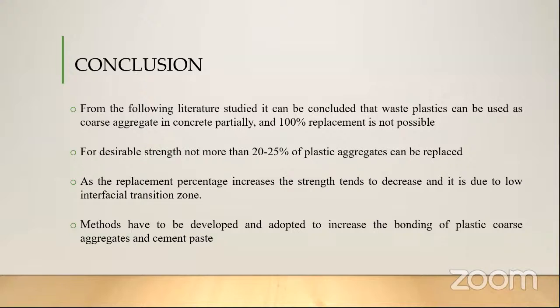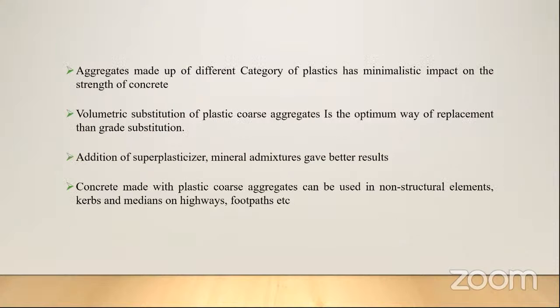So the conclusion derived from the literature is that waste plastics can be used as a coarse aggregate in concrete partially, because 100% is not possible. One of the major reasons is the low bonding between the plastic coarse aggregates and the cement paste, which leads to a weak interfacial transition zone. It was more of a unanimous finding among all the researchers that not more than 20 to 25% of the plastics can be replaced. This gives us an idea that we have to develop methods, or try hard, to increase the percentage of replacement of plastic aggregates.